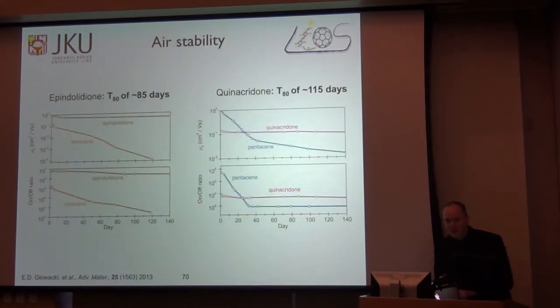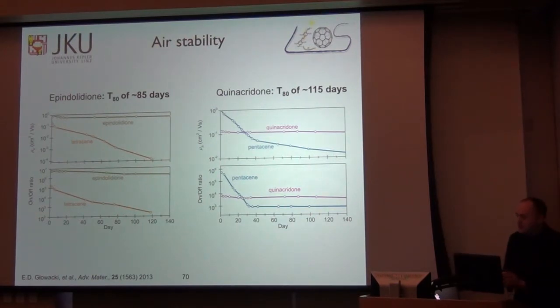But do they perform as semiconductors? And we made transistors, and if you look at the transistor performance, comparing tetracene to epindolidione, that 4-member ring has a mobility of roughly 1 centimeter squared per volt second, which is very high for organic semiconductors. Quinacridone is slightly lower than pentacene at about 10 to the minus 1. But if we look at the stability over 6 months, both the epindolidione and quinacridone are rock solid. They don't degrade whatsoever, whereas pentacene and tetracene degrade very, very quickly.